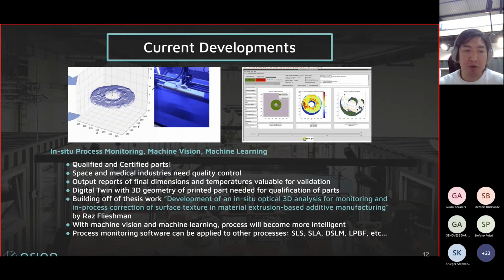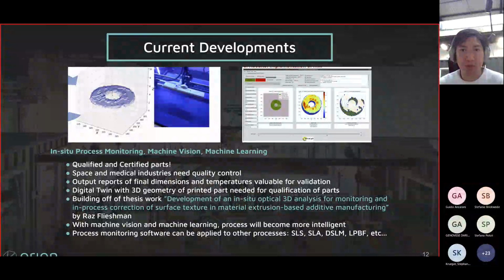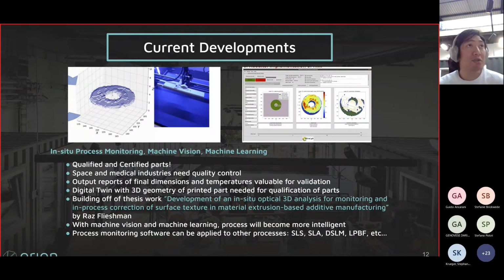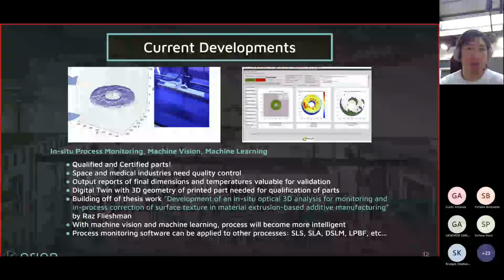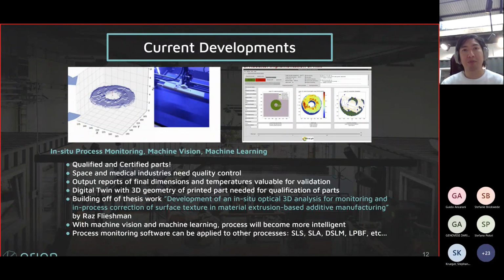So I think what we've managed to do in our process is show that we can consistently achieve high strength that is as good as, if not higher than, injection molding. And if we can continue to prove that, it'll be easier for us to certify parts directly out of the printer, so that we know our process is stable and able to consistently achieve these mechanical properties. But the other part of it is understanding: did our process introduce any errors or gaps or voids into the final product, and are the dimensions within the correct tolerances that we're expecting? So this is something we're also rolling into our developments: how do we monitor this process in situ, so that we can either correct it on the fly with in situ process monitoring, or at least have a warning that we did not meet our target dimensions?